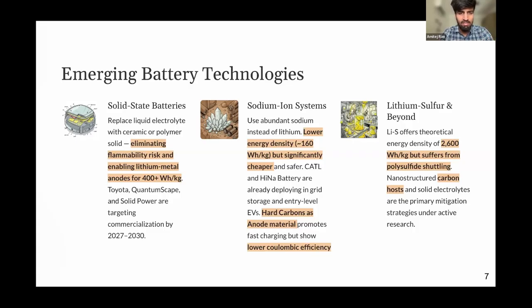and it uses hard carbons as an anode material. Hard carbons are generally made from lignocellulosic biomasses, converting them into specialized hard carbons which are battery grade. It requires a high amount of capex, high amount of tunability and customization, and it promotes fast charging, but it suffers from a lower coulombic efficiency if the quality is not up to grade.